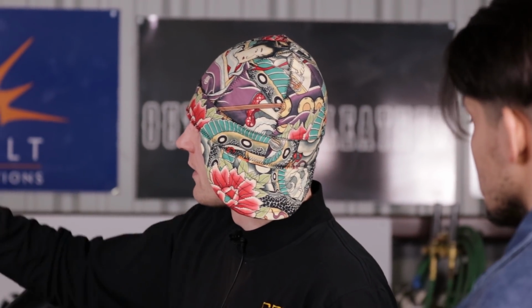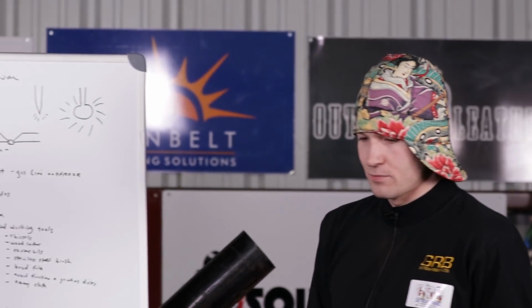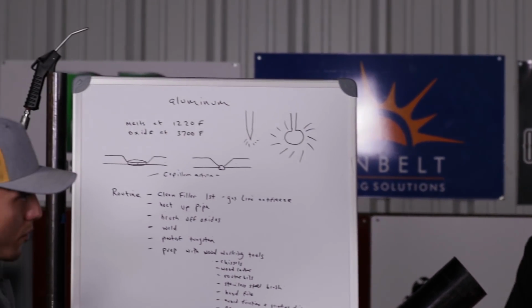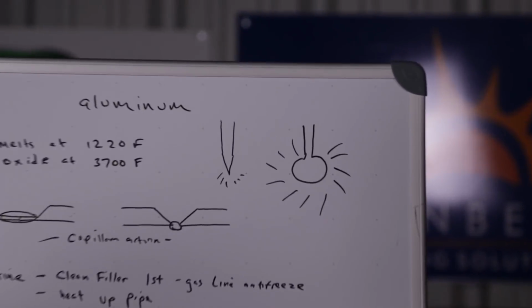It very much depends on the tungsten prep and also the kind of tungsten. I believe there's a manifold manufacturer on YouTube who has videos where he's tried different tungstens with different etching, and he's had different weld results with different tungsten and how they hold up at elevated temperatures. I've also found that 2% thoriated seems to crack in the middle when you have it at elevated temperatures.